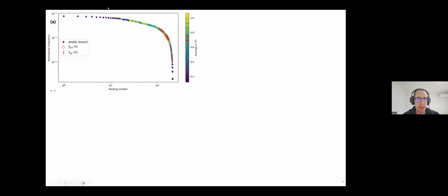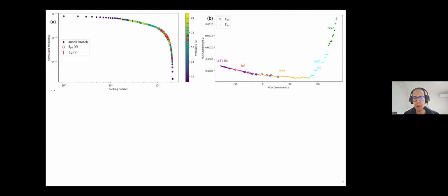This seems to be quite a smooth surface, but then we apply an unsupervised learning technique, very well known, PCA, which is very simple to employ nowadays to reduce the complexity of our data. And then our data is represented differently in this new two-axis space. And using yet simpler clustering algorithms like k-means and so on, we consistently realized that our data could be segmented, and it was segmented into what we call head, neck, core, and tail tip of the distribution.